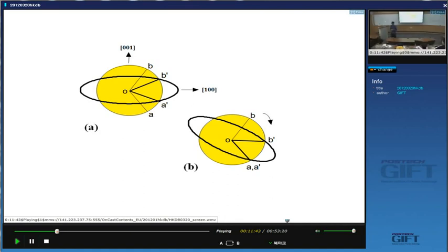These are not invariant lines. They are simply lines which are undistorted, but they are rotated. Okay? And rotation means that they don't represent coherent lines between the austenite and ferrite. And there is no way I can find even a single line which is undistorted and unrotated by the Bain strain. Okay? So the second problem with the Bain strain is that it does not leave any line invariant.